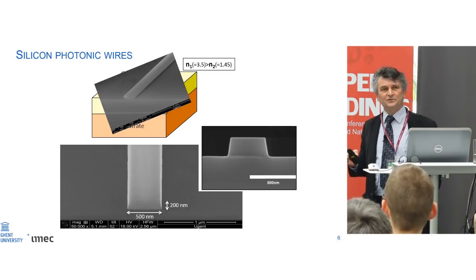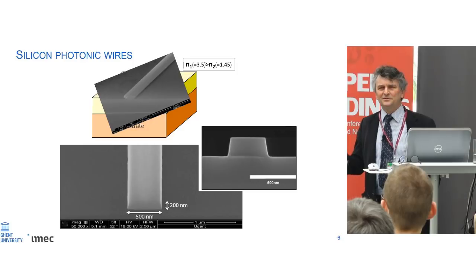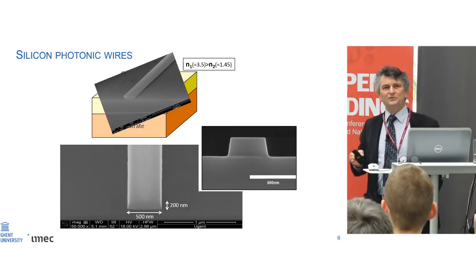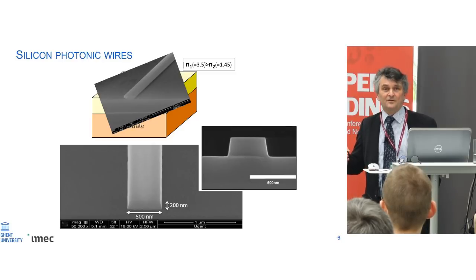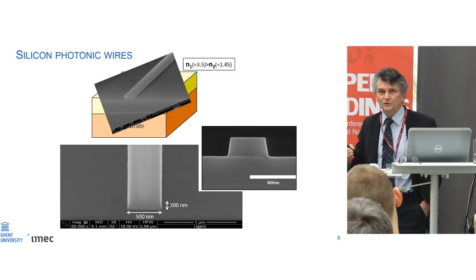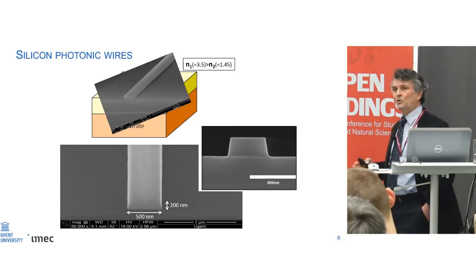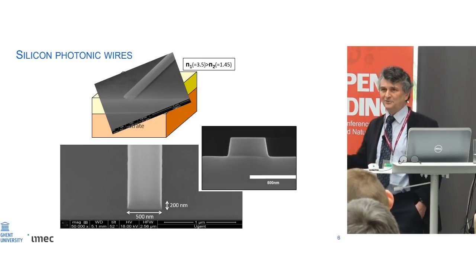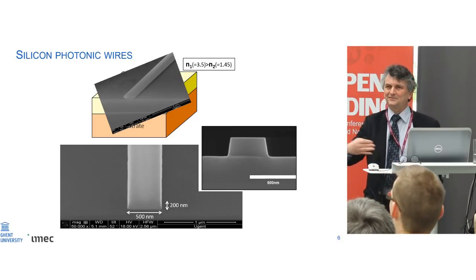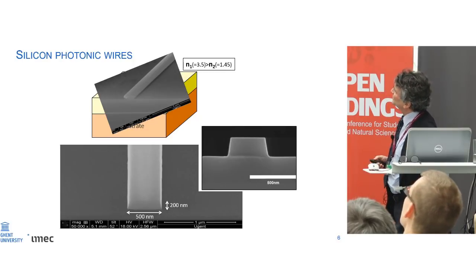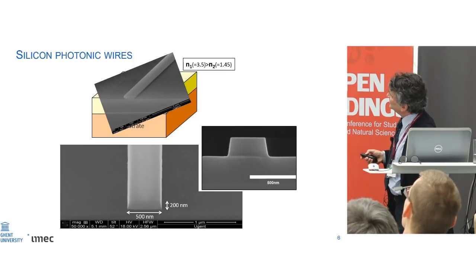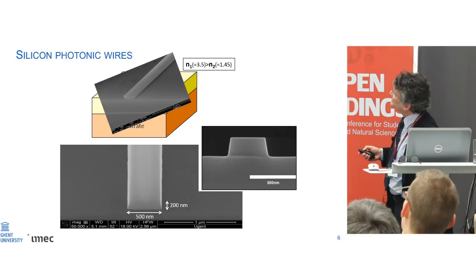The bend radius in an optical fiber has to be as high as 1 centimeter or so. In these waveguides, the bend radius can go down as low as 1 or 2 micrometers. So you can make almost abrupt bends, and light will not go out of the bend, will still, without any loss, follow the bend. So that's an important asset of these silicon-based waveguides.